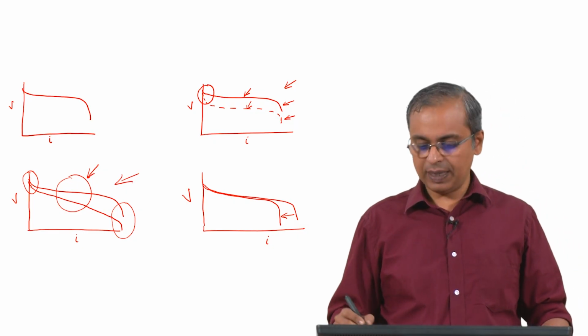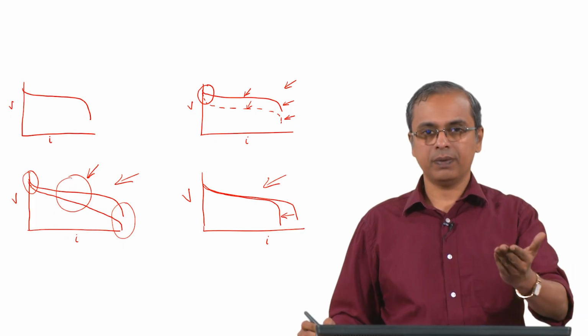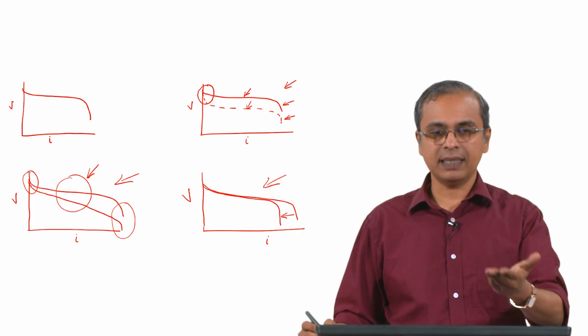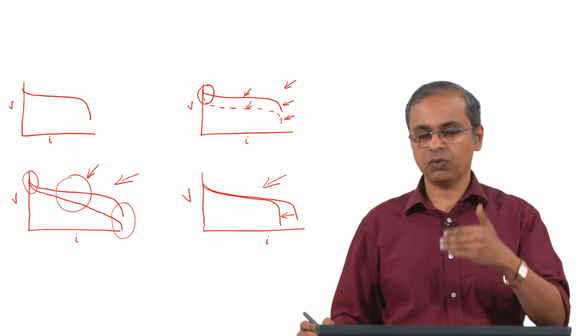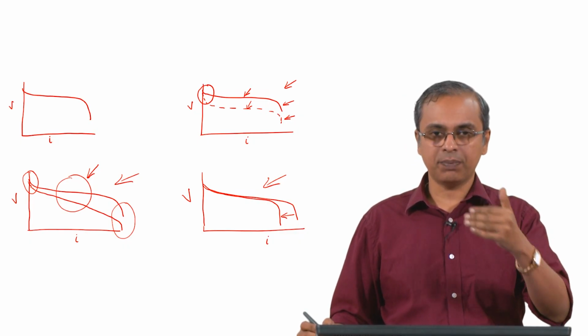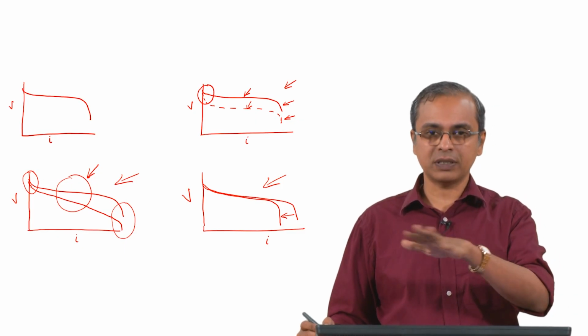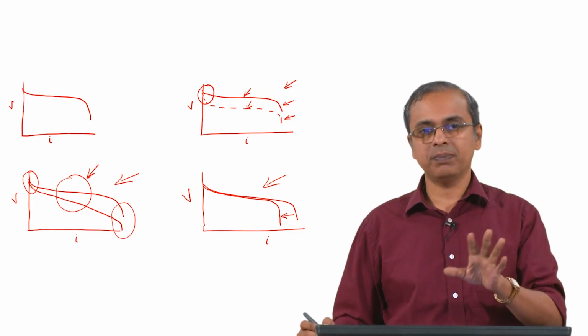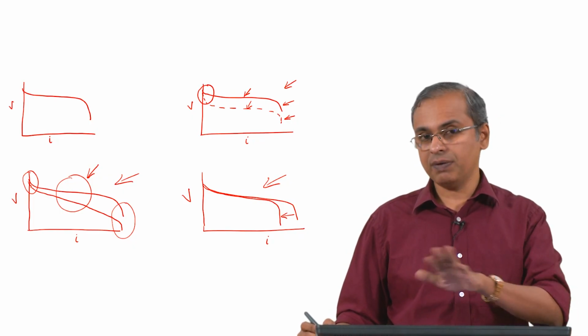And the third would be one where some pathway for the reactants reaching the reaction site is getting blocked for various reasons. It could be that some old reaction product has formed some irreversible reaction, or has left some precipitate which is blocking the path for these reactants, and therefore the pathway for the reactants has been blocked.